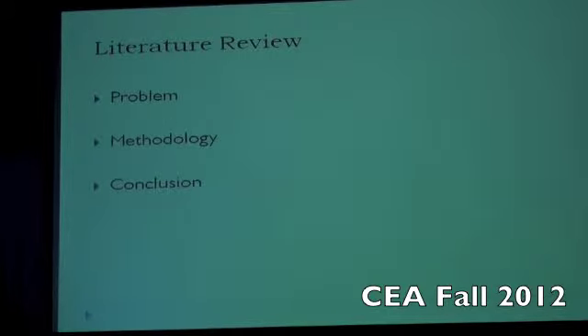The methodology was that they casted several different specimens with two plastic materials, ABS and PVC, with different slenderness ratios and different tube wall thicknesses. And for the reliability of the results, they casted 3 specimens for each slenderness ratio. The conclusion that they came with is that the plastic provided sufficient lateral support, which increased the ultimate strength of the concrete core. The increase in the concrete core strength was approximately found to be 3.25 times the burst pressure of the tube. And they recommended testing other concrete design strengths, which is what we're doing.